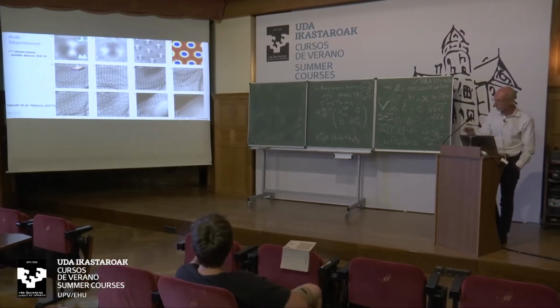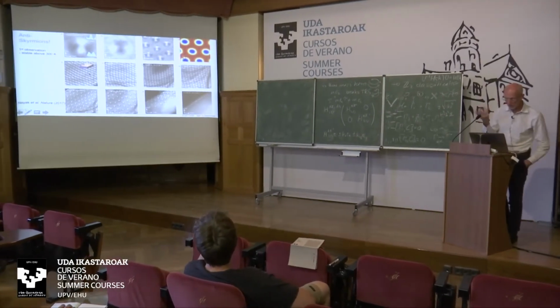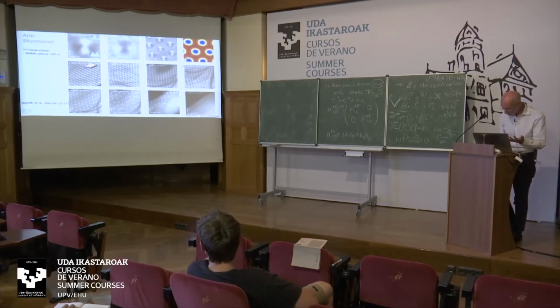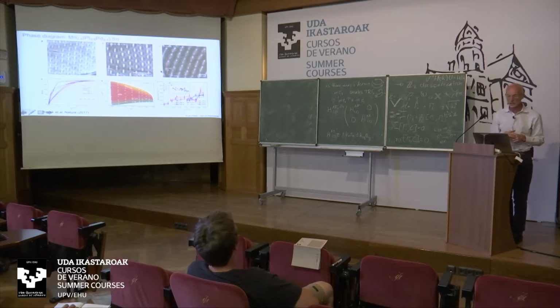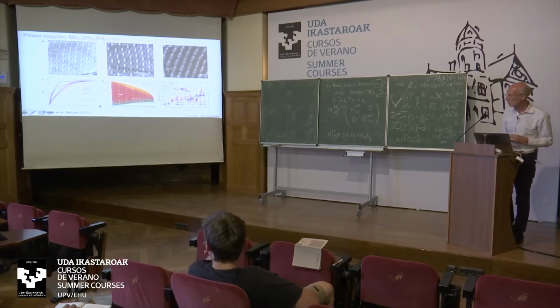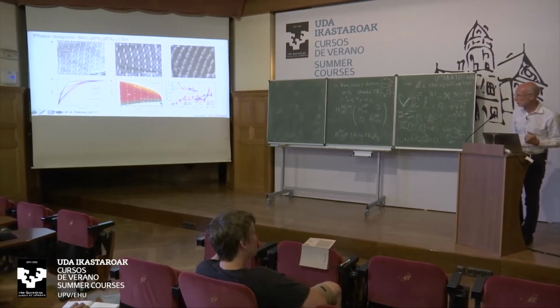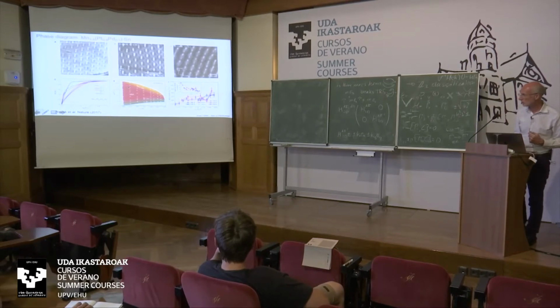And just like the skyrmionic phase, as you change the temperature or the field, you can change the stability of this phase. So this is just to show you that as we change the temperature or field, you can change the spacing and size of these antiskyrmions. In our system, we can only go down to 100 degrees Kelvin, up to 400 degrees Kelvin, and for perpendicular fields up to 0.6 Tesla. We basically see all of this region is where we see these antiskyrmions, and the green is where we see the helical phase.